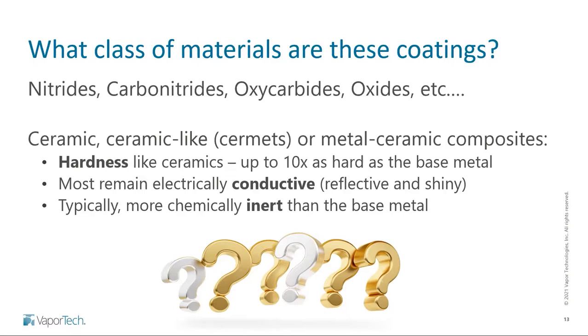Hardness can be as high as 10 times as hard as a base metal. Good example is titanium. Titanium metal itself, very soft. Titanium nitride, extremely hard. And like I said, most of these do remain electrically conductive, which allows them to retain their reflectivity and their shiny nature to mimic metals. And typically, these types of compounds are going to be more chemically inert than the base metal they started with. You know, a titanium oxide, titanium nitride is going to be more inert than a titanium metal, for example.